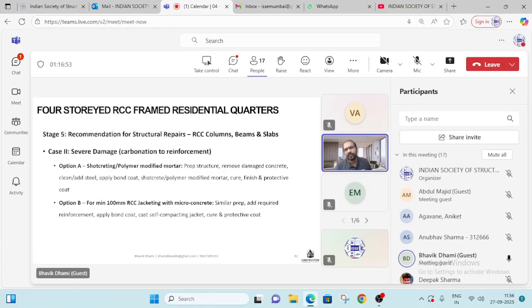For severe damage, where there was carbonation to the reinforcement, they have proposed option one and option two based on the depth of loss of concrete, or spalling of the concrete. If it is less, you can cover it with a polymer localized repair. If it is more, say a minimum of 100 mm, it would be best to go with RCC jacketing with micro concrete.